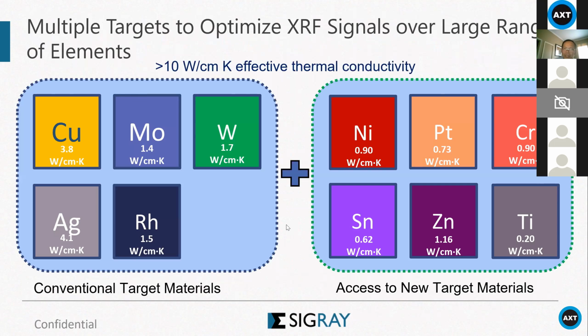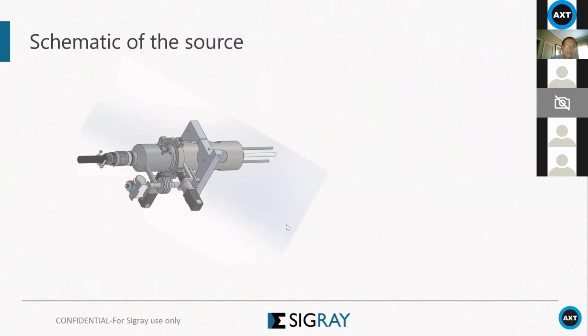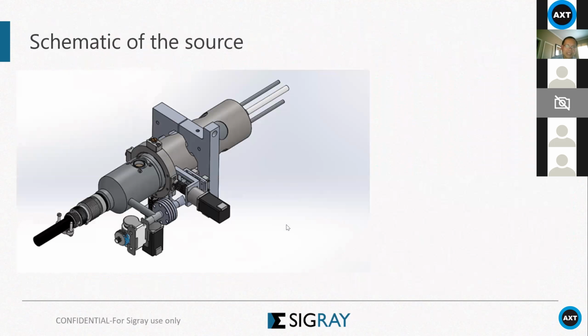we can also do other elements, mostly enabled by the microstructure, because, for example, some of the metals have very low thermal conductivity, like tin and nickel. We can still embed them into diamond and produce the characteristic lines we would like to have. So the source looks like that. The diameter of the source is like a Coke can. This source is the most powerful X-ray source developed ever for a sealed X-ray tube.